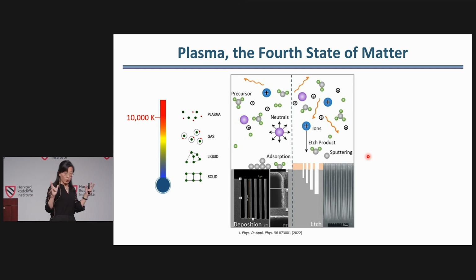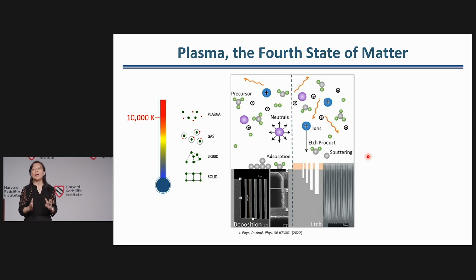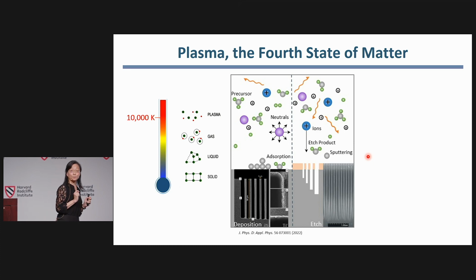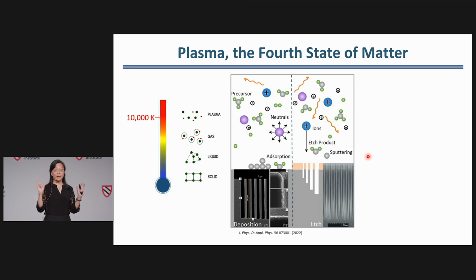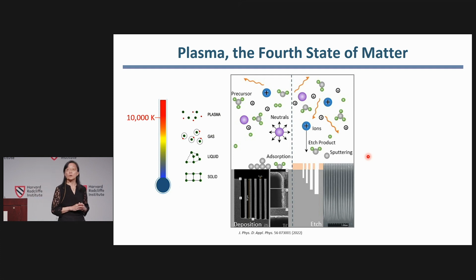These ions being charged, I can use an electric field to direct where I want them to go. And usually I want them to go perpendicular to the surface. Through the momentum transfer, I can dictate the direction of the chemical reaction. Giving chemical reaction a direction is critically important to pack a trillion transistors into your microprocessor. The radicals that we have in the gas phase are so reactive that they help lower the temperature on the surface that is needed for this reaction to take place. In many ways, it's similar to what a catalyst does, lower the temperature that is needed for chemical reaction to occur.